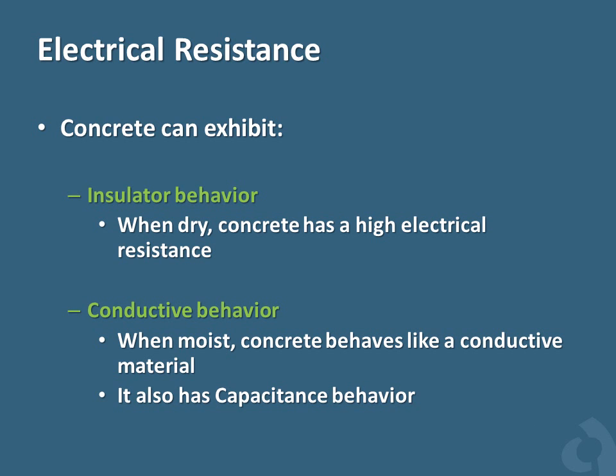In order to get into the electrical resistivity topic in concrete testing, let's begin with the electrical properties of concrete. The electrical properties of concrete largely depend on the moisture content of concrete. Depending on the moisture content, concrete may exhibit conductive or insulating characteristics. For example, a concrete sample might exhibit high electrical resistance when it is dry, but the same concrete can have much lower resistance if it is saturated. Moreover, concrete has capacitive properties, which means it can hold electrical charge.